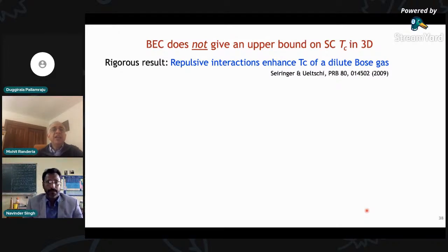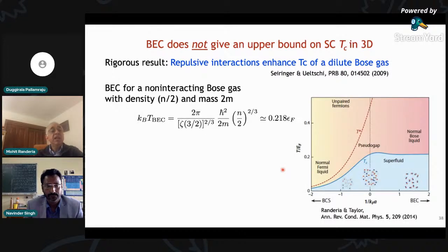So actually, this idea of what repulsive interactions do to a dilute Bose gas, although the dilute Bose gas at 0 temperature was solved by Bogoliubov in 1944, until the 21st century we did not know what the answer was. And finally, there's a rigorous result that repulsive interactions actually enhance the TC of a dilute Bose gas. So the non-interacting BEC is not an upper bound because it can be violated. And indeed, it is violated in this BCS-BEC crossover.